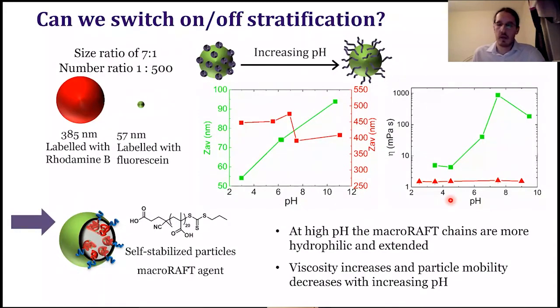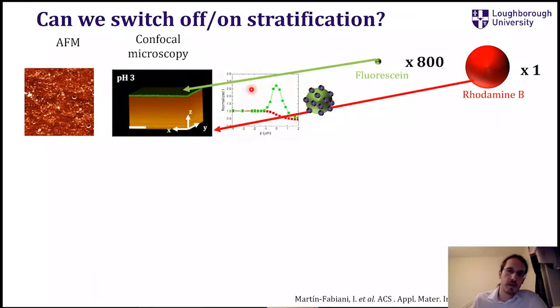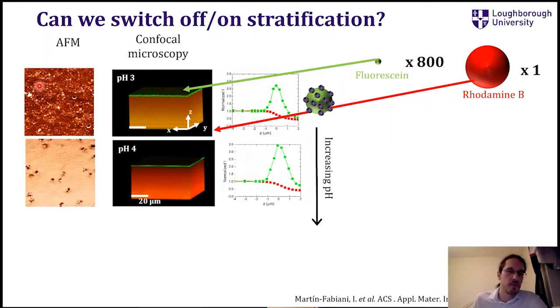So what I did again is blend these two particles and just keep the amount of particles constant, but change the pH. And again, I looked at the top using atomic force microscopy and at the inside of the coating using confocal microscopy. So when we have low pH, and in this case the green is really the small particles, we have stratification. We have small particles at the top, large particles at the bottom, and the top surface looks only small particles. If we increase the pH to 4, it still looks like we have stratification, we still have green on top, red at the bottom, but we start to see a few large particles at the top